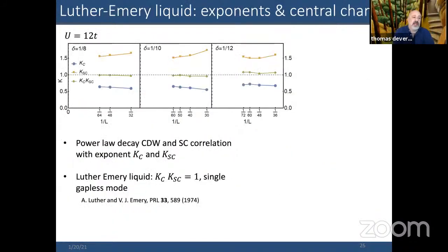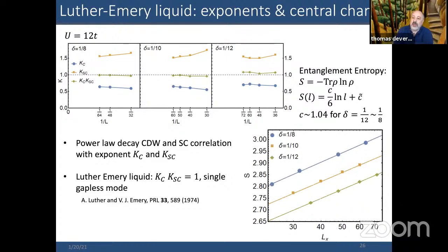And if you plot both the exponent that you get from fitting the charge order, which is long range or decaying as a power law, and the superconducting exponent, you find that the product of these two exponents is one. For different values of doping, here's 1/8, 1/10, 1/12. This is for U equal to 12t. So this is what one identified a long time ago as a Luther-Emery liquid, that charge order and superconducting order are dual to each other, with the product of the exponents being pinned at one, corresponding to a single gapless mode in the central charge. So that you can get by looking at the entanglement entropy, and you find that C is one plus a little bit of error for a range of doping around half filling from 1/12 to 1/8.